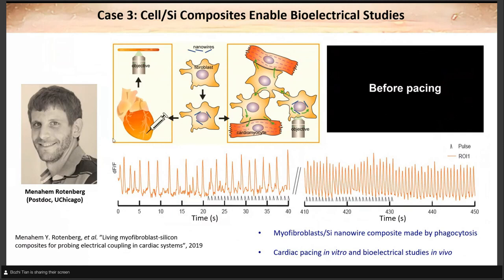at Technion very soon. So in this project, he created those hybrid myofibroblast and silicon nanowire composites through a phagocytosis process. And then he delivered those hybrid composites into either cultured cardiomyocytes or directly into the heart. And then he delivered the light pulse with a certain frequency, and that can trigger the elevation of intracellular calcium signals due to a combination of a photoelectrochemical and a photothermal effect. Then this induced calcium signal can be transmitted to other adjacent cells and eventually reach the cardiomyocyte.